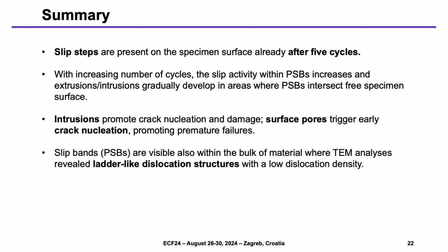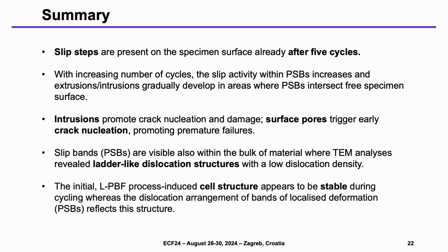And then using TEM, we were also able to describe, let's say, the dislocation arrangement within the bands, which are characterized by a low dislocation density and a ladder-like dislocation structure, which resembles the underlying cell structure, which appears to be stable during cyclic loading.